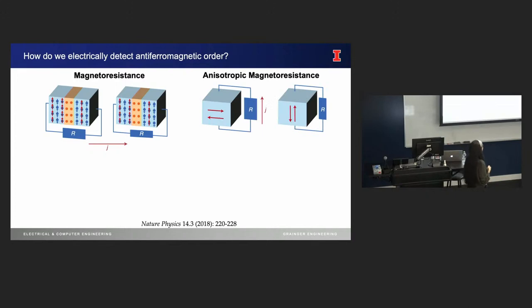Then we have anisotropic magnetoresistance. These are all resistive measurements. What these measurements are doing is they are trying to understand how does magnetization affect the resistance of the stack. So in this one, essentially, this resistance depends on the orientation of the Néel order, which is the antiferromagnetic order, and the direction of the current. Now this one, the AMR, this is a bulk phenomenon. It has been observed experimentally, but it is a very weak effect.